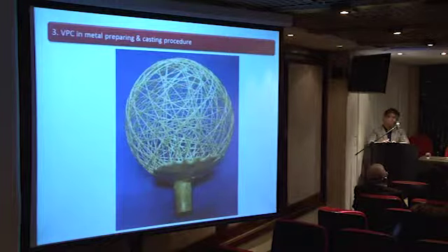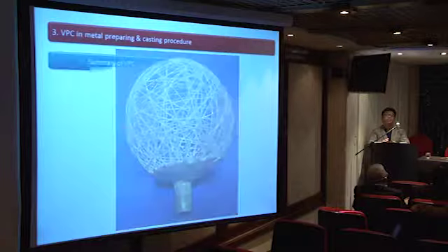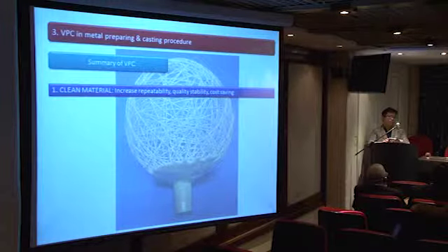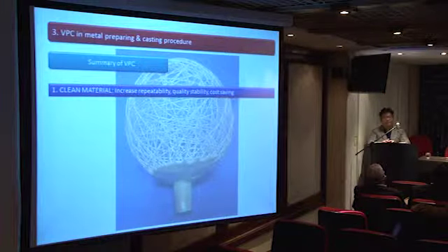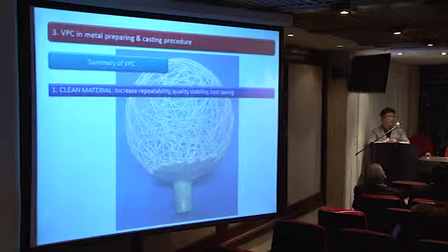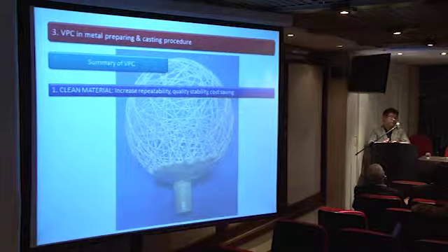These are some samples that we did on the casting. This is about 0.2 millimeter thick, where again, we need a very good process and procedures for the casting to achieve a good filling and a smooth surface.